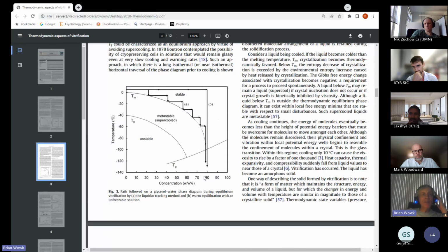So what happens is once you start getting into the sub-zero temperature ranges, if you're adding higher concentrations of the CPA, you're not actually getting more CPA into the cells. What you're doing is you're osmotically removing water.